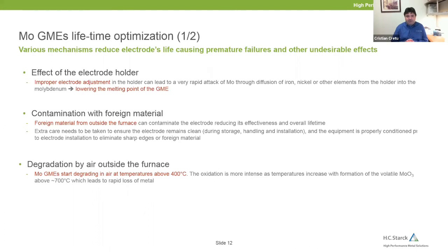Degradation by air outside the furnace: below 400 degrees Celsius, molybdenum is fine. When you go above that, things start to happen, and especially above 700 degrees Celsius, which is nothing for molten glass, you start forming molybdenum trioxide. It's a sublimation, so it goes from solid directly to gas, and you will see a very interesting smoke. Yeah, it is typically not a good thing to see this because your electrode is about to be destroyed.